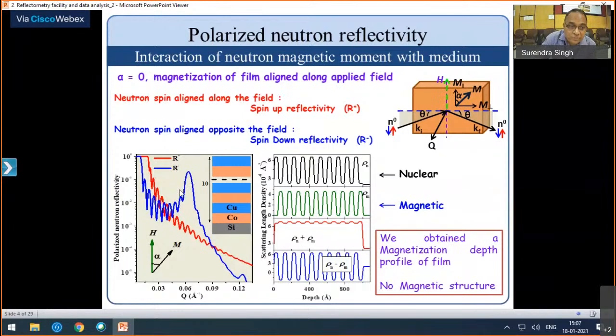So we have this first Bragg peak over here, and the 0th Bragg peak is at theta c. The number of oscillations between these two will be n minus 2, where n is the number of bilayers in your multilayer. In our case, there were 10 bilayers, like cobalt, copper, one bilayer, then another bilayer - there were 10 like this.